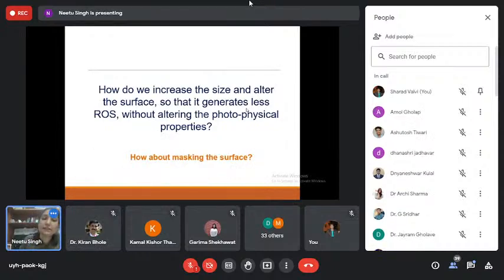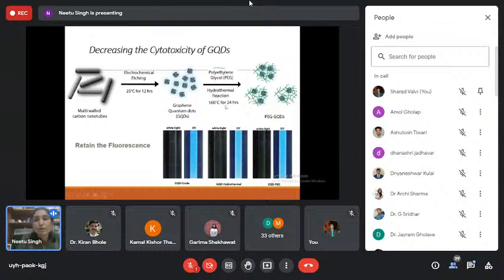So now the question is, we want a carbon dot or a quantum dot based system. You want to keep the size small, but you want to create some masking of the ROS. So the ROS should not get catalyzed on the surface. So very simple, we thought of putting a polymer coating on it. Remember, we are not the first ones to put a polymer coating. Many people have thought of it. They have done it. However, if you have a very thin layer of polymer coating, it is not enough for the ROS to get quenched.